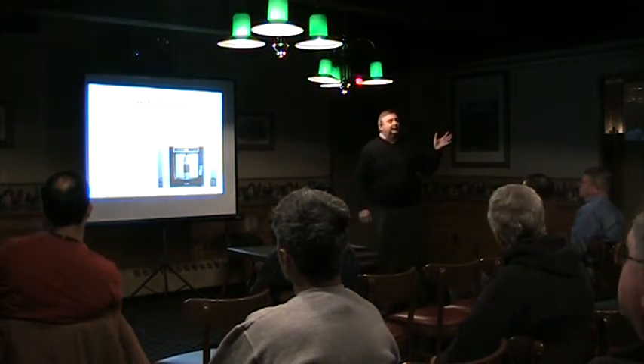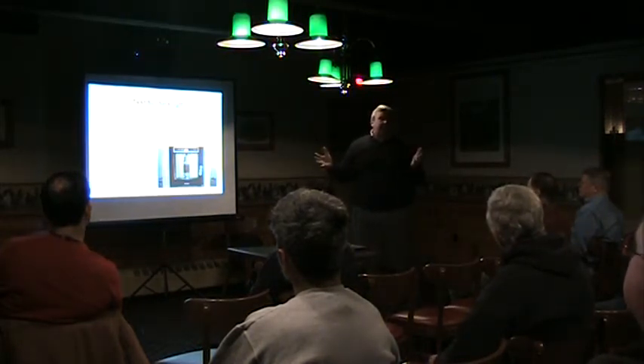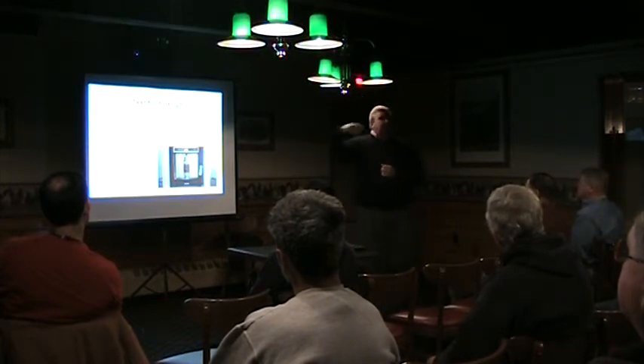Now the unconfined compressive strengths are basically what they are as concrete cylinders. And we're going to make those cylinders, we're going to do three different samples using 3 different dosage rates of cement, percentage-wise. And then we're going to do 7-day breaks. 5% may come out at 600 psi, and we're going to say, no, that's too high. We don't want that much cement in this procedure. But we want to be somewhere in the vicinity of 400.